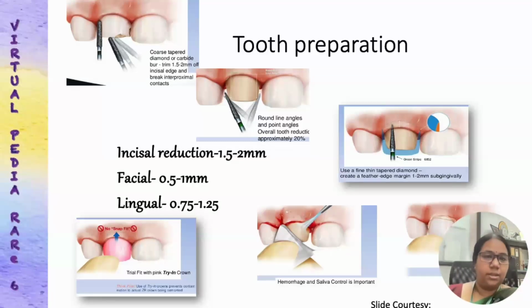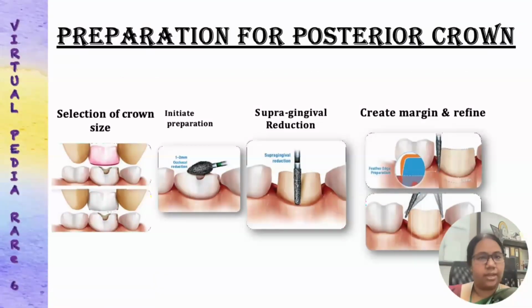When it comes to the preparation for a posterior crown, just like in the case of stainless steel crowns, we start by looking at the mesiodistal width and selecting a crown. The preparation begins with occlusal reduction following the occlusal contour, but by experience, and not what the manufacturer says, we all know there is a lot of tooth material loss in the case of zirconia crowns. After initiating the preparation and doing occlusal reduction, we do supragingival reduction, and finally we create a margin which we have to refine.